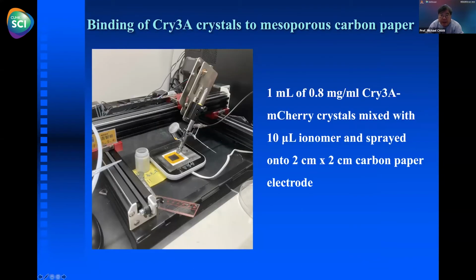So here's the apparatus used to do that. Here's the carbon paper that they're going to use to make the electrode. They spray the Cry3. For these studies, we used mCherry crystals because they're fluorescent. We sprayed Cry3 mCherry crystals and the ionomer onto this surface to get an even film. And then we tried to look for whether the crystals would stick.